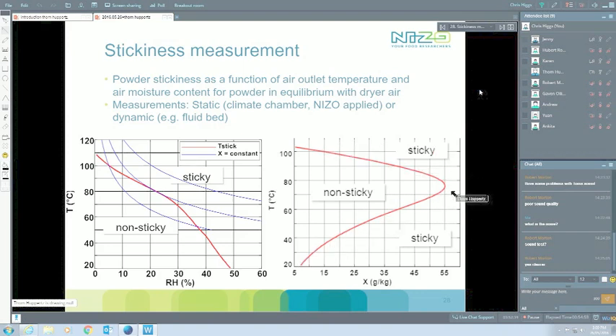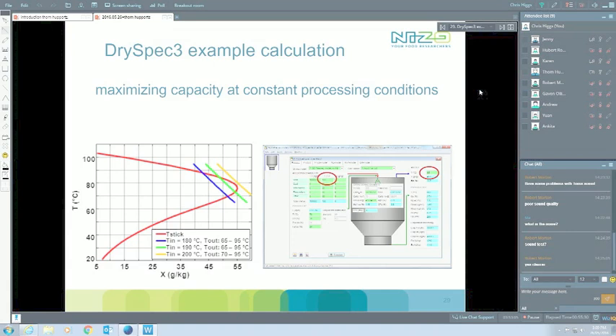Basically anything on the right hand side of the line will give sticky powder, so that's very much a risk zone. Anything on the left hand side is the non-sticky zone, that's where you want to be. And once you know where that is for a specific powder, then you can look at how I can change my dryer settings to be there. Because of course this is sticky or non-sticky, but capacity is the other issue. And you can start running your simulations and see, am I in the safe zone or not?